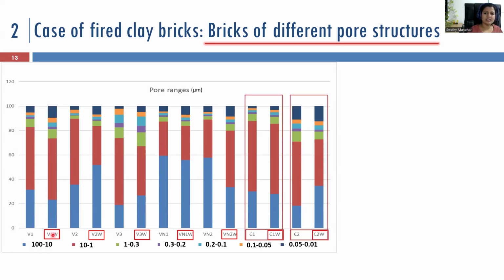What I want you to see is the last two cases, samples C1 and C2, which have larger pores in C1 and smaller pores in C2. After weathering, in C1 the macropores remain the same; there is no much change in the macropores, only small redistribution in the microporous range. Whereas in C2, macroporosity increased so much, almost doubled.